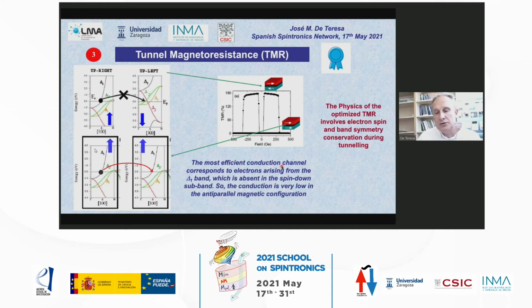And the most efficient conduction channel corresponds to electrons arising from this delta 1 band or subband, which goes in the parallel configuration to the same band in the second electrode. So this is very efficient conduction. This is why the resistance is low in the parallel configuration. But in the anti-parallel configuration for the spin down subband, this delta 1 band does not exist at the Fermi level. So this very efficient conduction channel does not exist in the anti-parallel configuration. So there are other conduction channels which are less efficient, and this gives rise to a very high resistance.